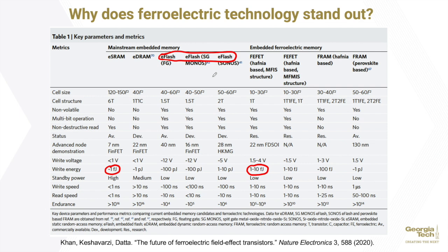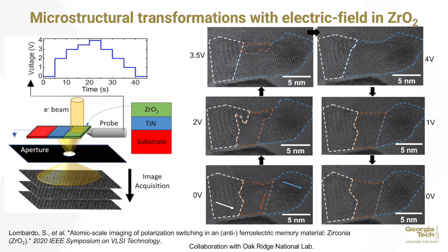However, there are important differences between a ferroelectric field effect transistor and a standard high-K metal gate logic transistor. In logic transistors, extreme measures are taken to make sure that the Hafnia and the zirconia layer remains amorphous. On the other hand, ferroelectricity is a structural phenomenon, and as a result, the oxide layer needs to be crystallized. And in an FE-FET, due to the lack of an epitaxial template, these layers are inevitably poly or nanocrystalline, with the crystallite size ranging between 4 to 100 nanometers.